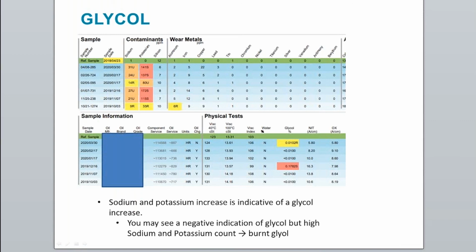This report is an extreme example. Coolant contamination can result from defective pump seals, improperly torqued cylinder heads, or cracked heads or block. In any case, the first thing you should do is resample to confirm that there's actually a coolant leak. If the report continues to indicate coolant, the next step is to shorten the oil drain intervals and oil sample intervals to at least half until the glycol is normal. And while this is happening, you should try and find where the leak is.